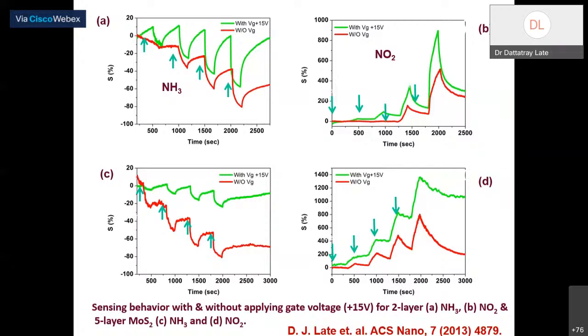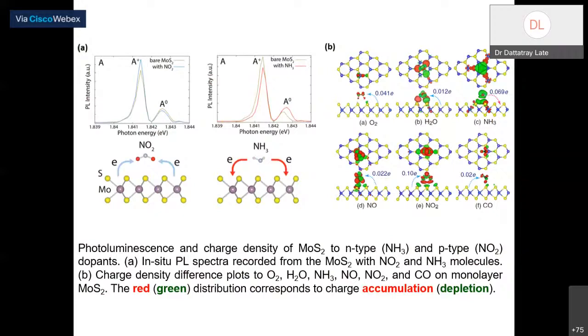Some materials are not sensitive enough to be detected by the sensor, so I am applying some gate voltage so that the sensor can detect the gas molecules being present. That can give you some kind of signal. Basically, what happens at the molecular level? The NO2 molecule or ammonia molecule just comes and sits on the MoS2 layer, and there is a slight change in the Fermi level.